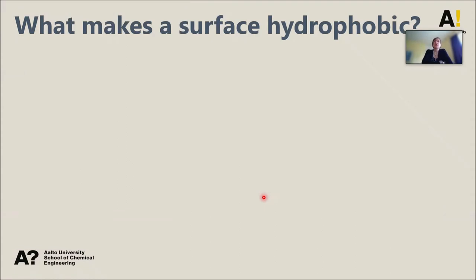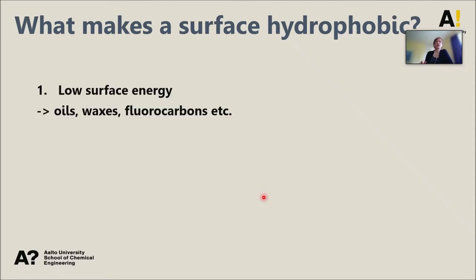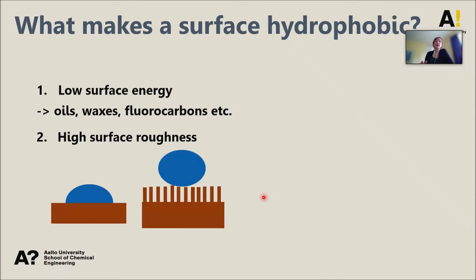So what makes a surface hydrophobic? To make a surface hydrophobic, you need, first of all, to have low surface energy. For this, you can use different oils, waxes, and fluorocarbons, which are unfortunately used a lot in textiles and in other materials, but they are not very sustainable. So of course, we want to use more, for example, bio-based materials. But if you have a smooth surface and only low surface energy, you can get a water contact angle of around 120. If you want to go higher, you need to add also surface roughness.